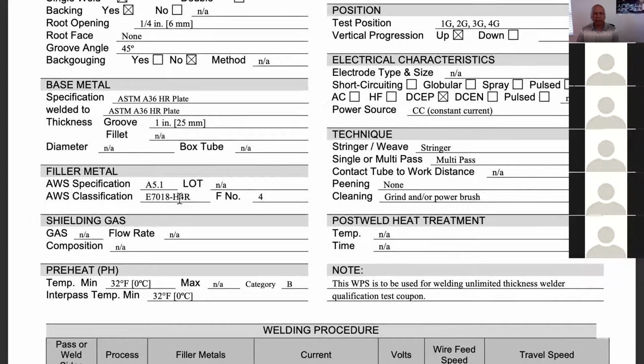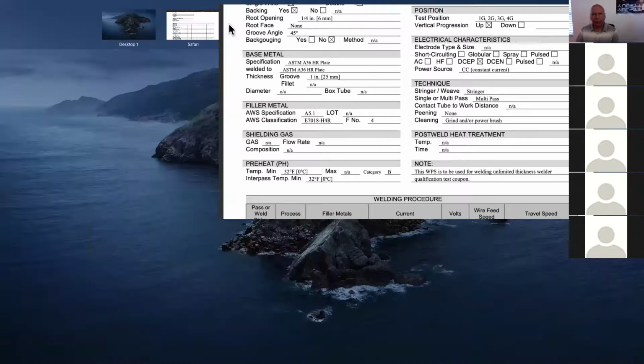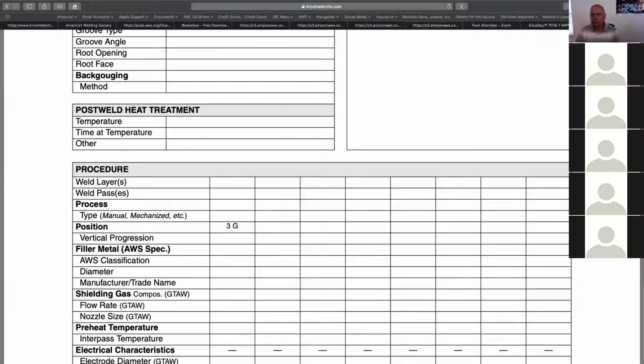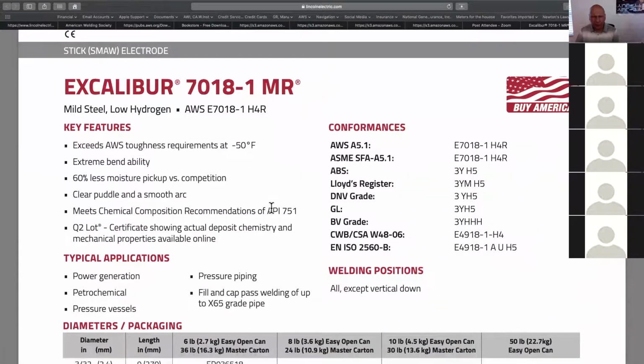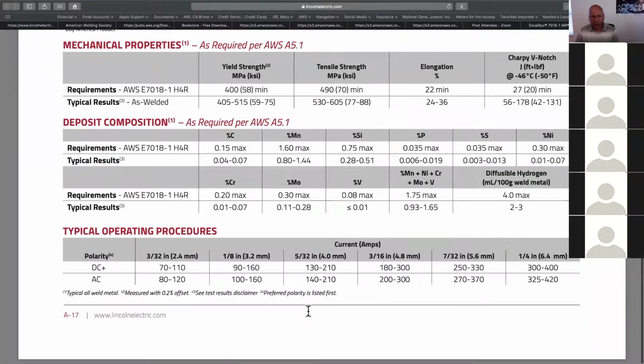We do use the E7018 H4R. H4R means it has a really low hydrogen diffusible level. H4R means that the diffusible level of that electrode is, so we here have a 7018 H4R. That means that when we look at the deposit composition, it has a diffusible hydrogen it's required to have no more than 4 milliliters per 100 grams of weld metal. In this case, Lincoln Electric gets the results of 2 to 3 milliliters. So they actually exceed that. They're able to produce a weld with very low hydrogen diffusible levels.